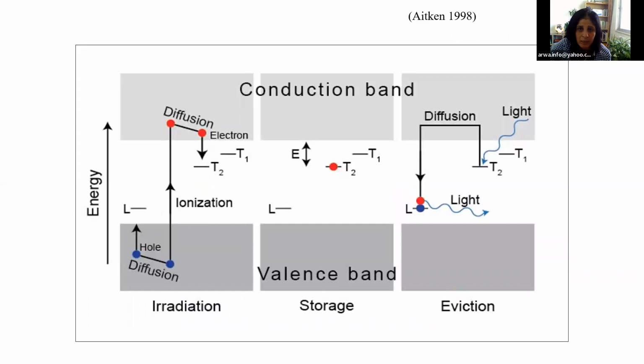The physics of this phenomenon, the luminescence signal, is usually understood on the basis of the energy band model. Minerals like quartz and feldspars contain lattice charge defects formed during crystallization or subsequent exposure to ionizing radiation. These charge defects are potential sites for electron storage with a variety of trap depth energies.